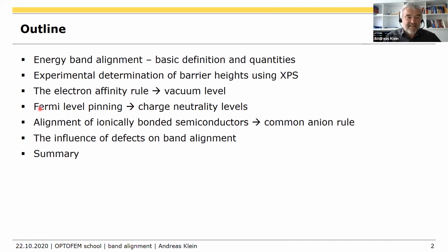Still, even if we say that the intrinsic pinning is not present in the ionic semiconductors, there is a pinning, and this pinning is induced by defects because, in contrast to the covalent semiconductors, it's usually very easy to form a defect, let's say a vacancy or something like that, in a more ionic semiconductor. And these also influence the band alignment, the effective band alignment and the barrier heights. And particularly when it comes to transition metal oxides, you will see that that can have quite severe consequences. They confine the Fermi energy, and that can have severe consequences for any photovoltaic applications.